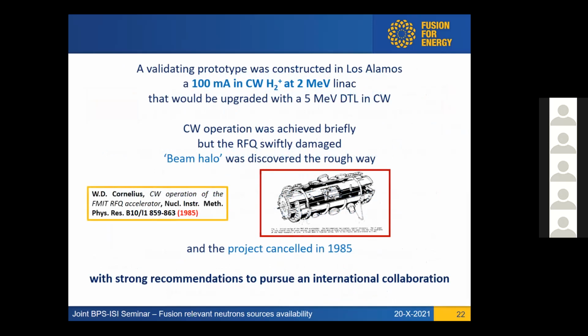And they constructed an RFQ. They were expecting to validate 100 milliamps in CW. Instead of using deuteron, they decided in a clever manner to use H2+. To be honest, this is also something that shocks me. It's true that the beam physics was not properly understood at the time, in particular what concerns the beam halo, which is a phenomenon that appears when you have high currents at low energies, driven by the space charge phenomena because of the repulsion that the particles start to have between them, and some of them are kicked away.